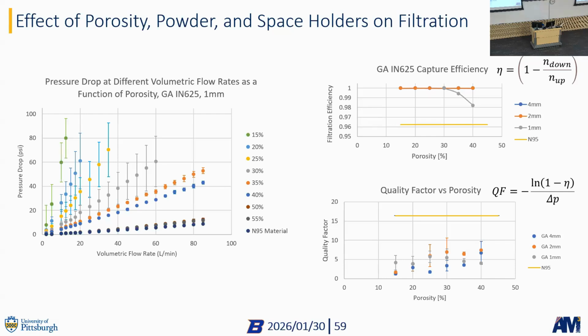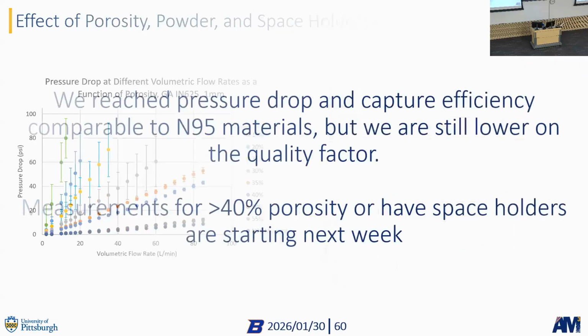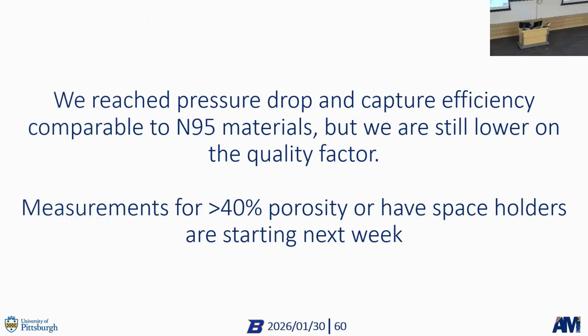Quality factor is not that good yet, at least not for these materials, because we haven't tested higher porosities yet, and we haven't tested the space holder materials yet either, right? But this is very good data, and Sam, if you see this on YouTube, I hope it only gets better, right? So we reach pressure drops and capture efficiencies that are comparable to N95 masks. The quality factor is still a little bit lower, but hopefully with the higher porosity materials we will see exactly what we need to have, right?